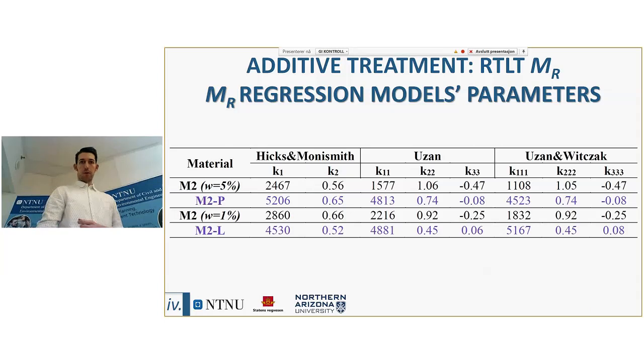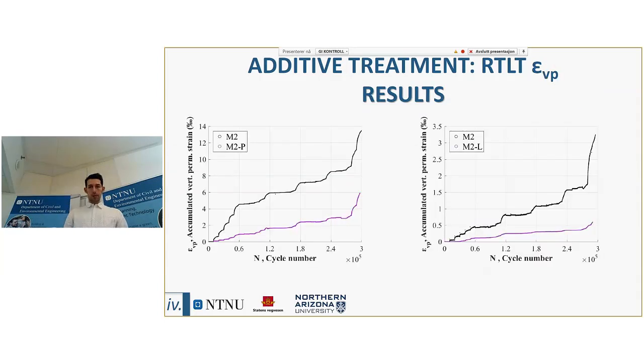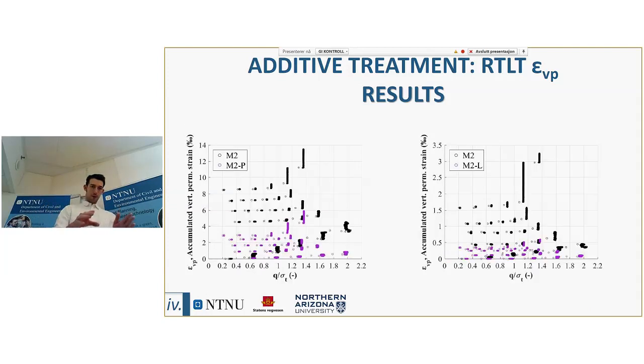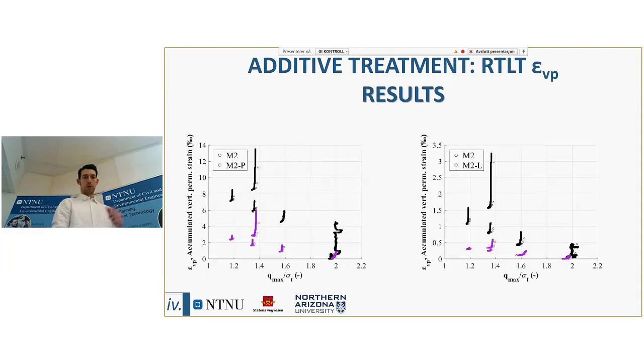Here we have some parameters connected to the regression analysis. The other key mechanical property, as mentioned, is the permanent deformation. Again, first and foremost, we display the results coming from the Tri-axial load test experiments. Here we portray the same results, but with different values along the x-axis. For example, here we portray the ratio between the deviatoric stress and the Tri-axial stress. And here, the ratio between the maximum deviatoric stress and the Tri-axial stress.